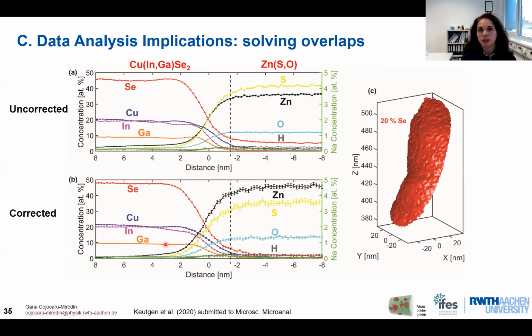And therefore, knowing exactly what the composition of this PN junction or this hetero interface is would be very important for the community. First of all, from the uncorrected proximity histogram here, we see clearly that the zinc content inside the absorber is really very low, lower than should be expected, so zero or a bit lower. And we see also that we get a lot of selenium inside the zinc sulfur oxide, and this is because of some overlap between selenium molecular ions and sulfur molecular ions.